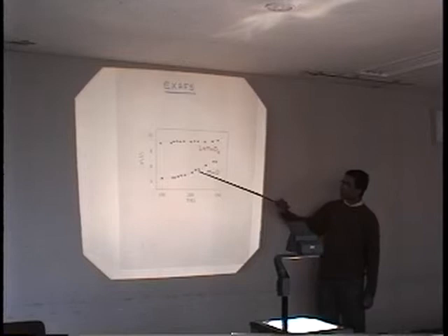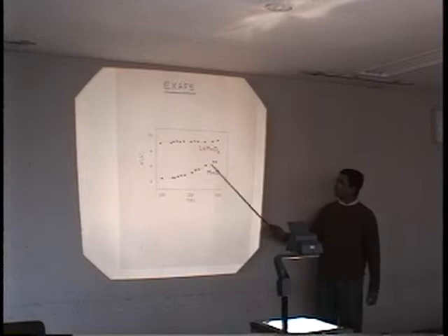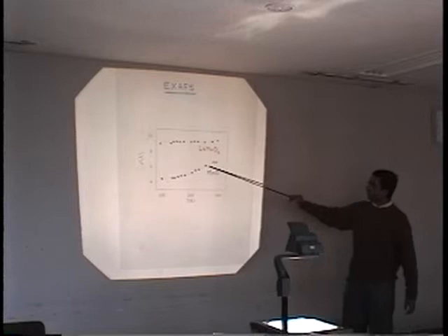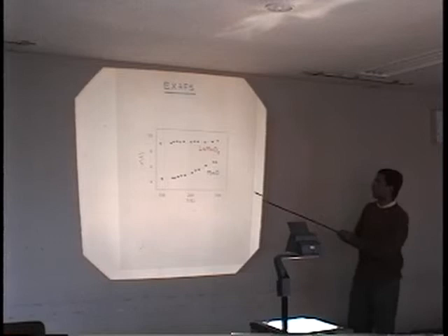And this decrease fits very well. This dashed curve is a fit through the data points assuming a correlated Debye model, which is the applicable model in this case. And you find that this disorder is essentially electron-phonon interactions, the phonons showing up in this way.